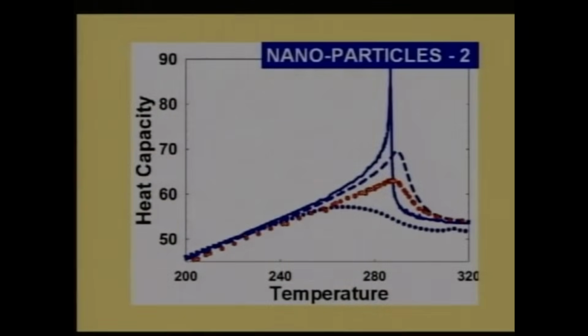And that's no mean technical feat to do. But there is a surprising difference in the heat capacities. As before, the new red curve gives the new results, the new nanoparticle measurements, and the blue curves are data shown previously. The peak shape and the peak temperature from the new nanoparticles much more closely resembles the powders, which remember are bigger by a factor of 1,000 than the other nanoparticles.